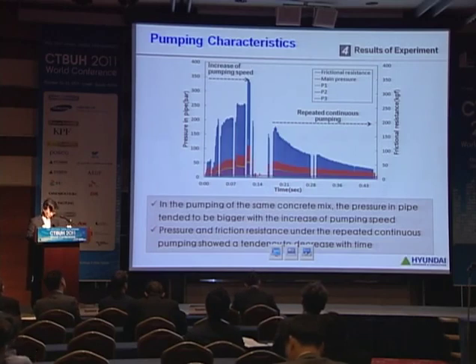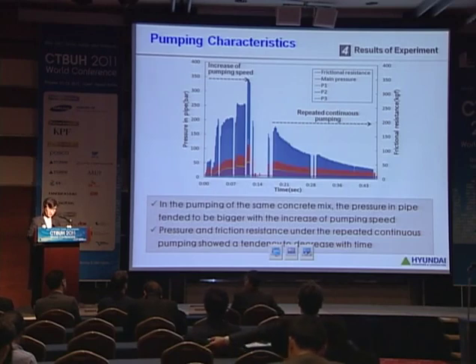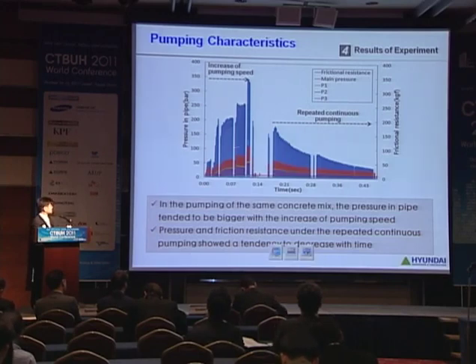In the pumping, with the same concrete mix, the pressure in the pipe tended to be bigger with the increase of pumping speed. And pressure and friction resistance under repeated continuous pumping showed a tendency to decrease with time. In this graph, the x-axis is elapsed time, and the y-axis is pressure in pipe and frictional resistance, respectively. This part is pressure in pipe, and this y-axis is friction resistance.